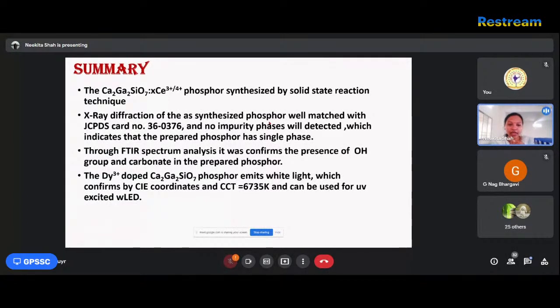And the FTIR spectra analysis confirmed the presence of hydroxyl group and carbonate in the prepared phosphor, and the dysprosium doped calcium gallium silicate phosphor emits white light, which was confirmed by the CIE coordinates. Thus, the prepared phosphor can be used as UV excited white LEDs. Thank you.